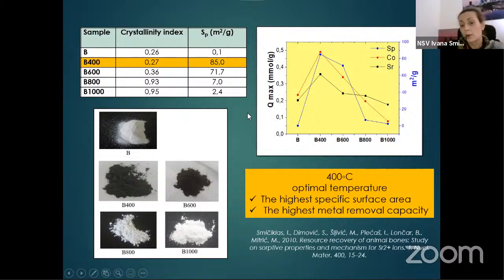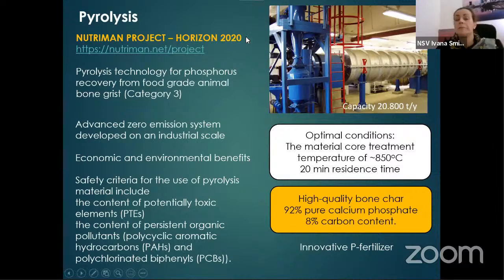However, in our work that was conceived after that, we have examined the capacity of these materials to sorb heavy metals and radionuclides, and it was confirmed that the product which exhibits the highest surface area at the same time is the high capacity sorbent for various heavy metals and radionuclides. The conclusion was that the mild temperatures of about 400 degrees are optimal for obtaining the material with the highest metal removal capacity.